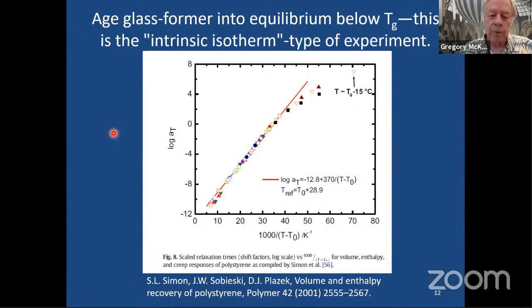Shortly after we did that work, Cindy Simon and her student, Bill Sobieski, and Don Plazek published some work looking at a compilation of data from the literature. Here is the shift factor versus 1000 over T minus T0, which is called a Vogel-Fulcher plot. It should be a straight line if it's really Vogel-Fulcher behavior. They found that the equilibrium data at about 15 degrees below Tg has fallen off this line, similar to what I just showed you. So they're again seeing a deviation from the expected Vogel-Fulcher, in a way that the times are shorter, not longer, than the extrapolated Vogel-Fulcher behavior.